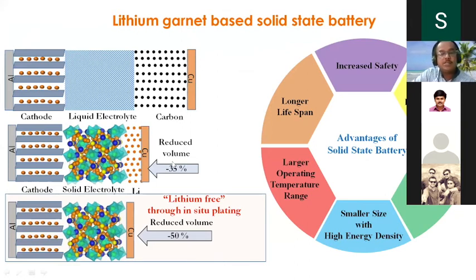You can reduce the volume by 35%, replacing carbon with 50 to 20 micron of metallic lithium, which is sufficient. I could think about making the solid state lithium battery. These are well-known demonstrated techniques. I don't require anode-free lithium batteries. This has been demonstrated long back, 20 years back. So what you require is the lithium.